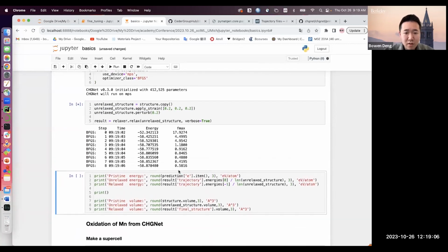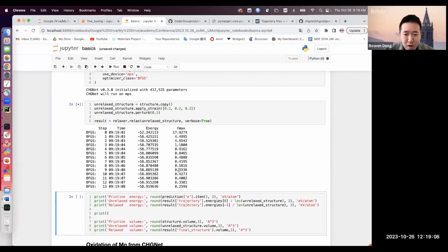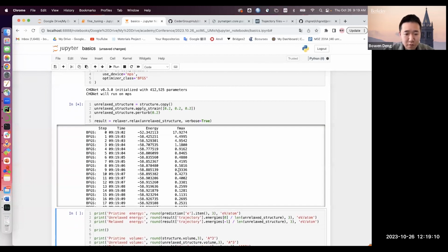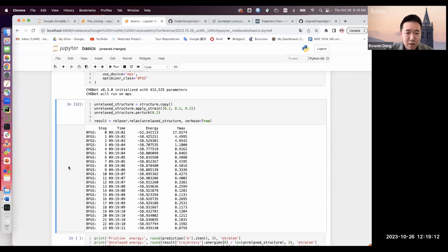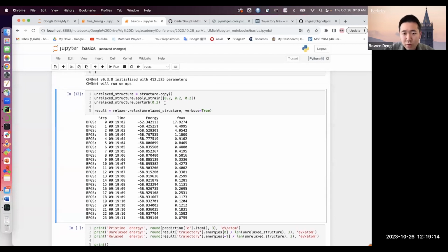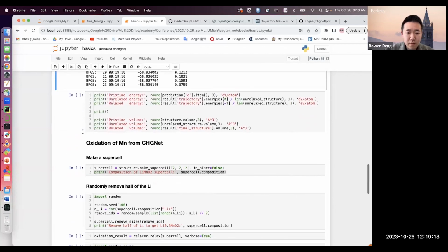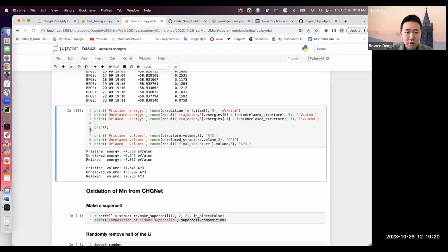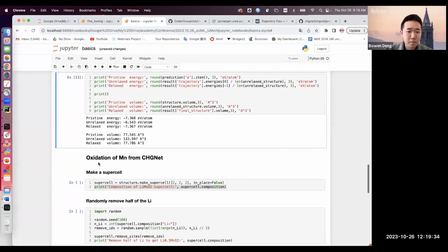And you can see the relaxation happens on the order of seconds. In a few seconds, the relaxation will be complete. And we actually applied a considerable amount of strain in the structure. If you print the initial and final result, you'll see that the relaxed energy gets back to the pristine energy. And also the volume, we basically doubled the volume, and it gets back to the initial volume.